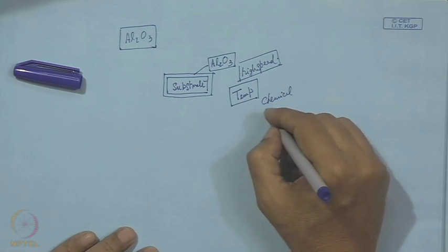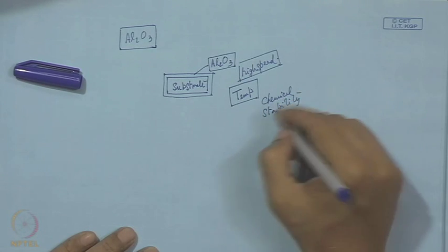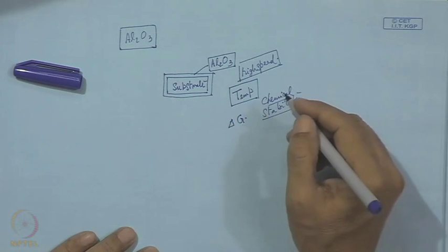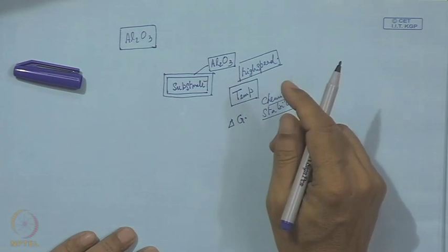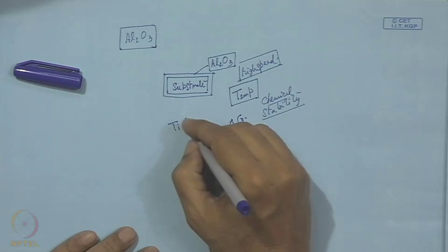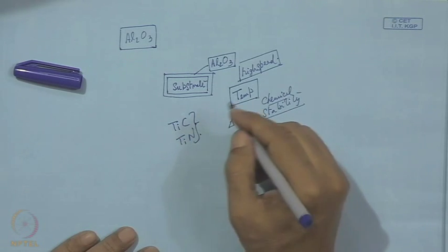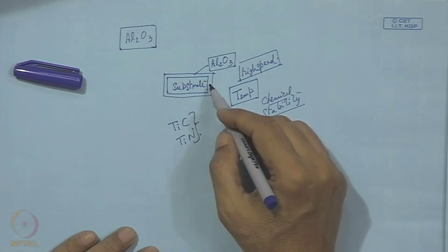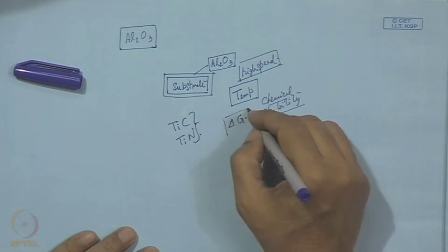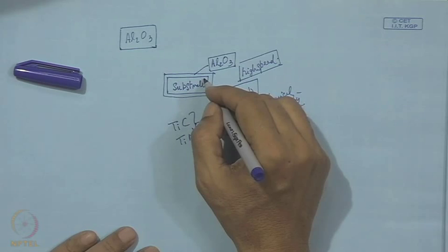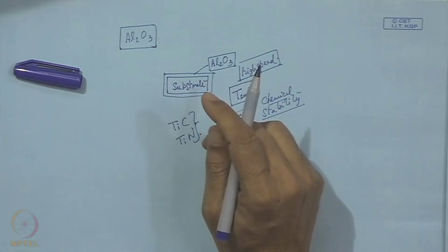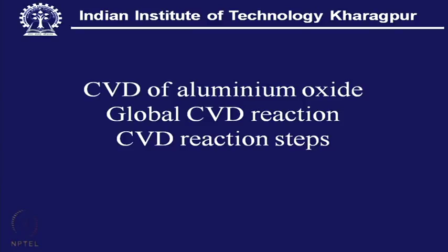This chemical stability is very much associated with the free energy of formation of the particular compound, and in this case aluminium oxide has a clear edge over TiC or TiN, which are already two useful materials as coating on the cutting tool. Now, this aluminium oxide needs to be deposited on the substrate. Here we can see that CVD can be a very good way of handling this coating technology and coating process.